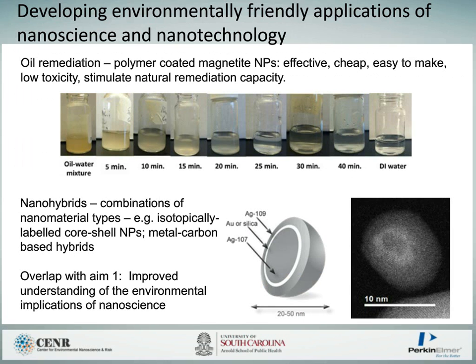And just to give you a couple of examples of the work we're doing here, the first one at the top is work with oil remediation. So we're using polymer-coated magnetite nanoparticles for oil remediation in natural systems. And we're particularly focused on this area because it's an effective, cheap way of remediating oil in natural systems. It works under natural conditions, which are very challenging. They're easy to make and cheap to make. They have a low toxicity.